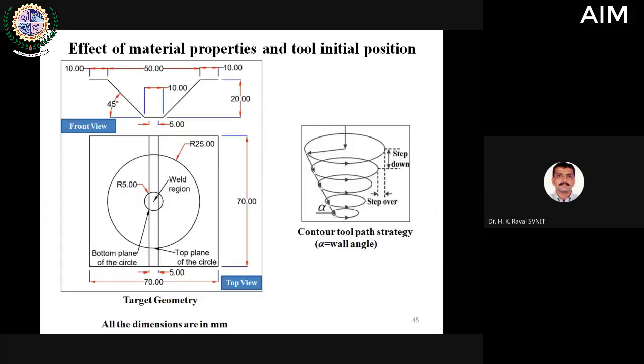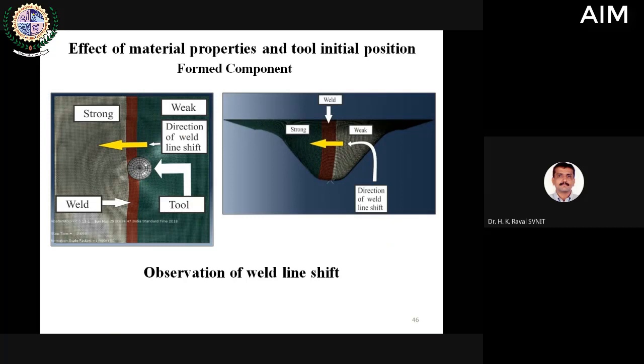And then the control tool path, as was discussed earlier, the result was found to be better in the hemispherical tool with the control tool path. So the same strategy was extended here. Geometry was taken as a cup cone and circular cup, and then the forming was done. This is the observation of weld line shift. One can notice here that the weld line is deviated. You can see it is a vertical line, it gets deviated. It's very clearly visible here. These are tool motions, the tool path for the tool motions on the panel directions.